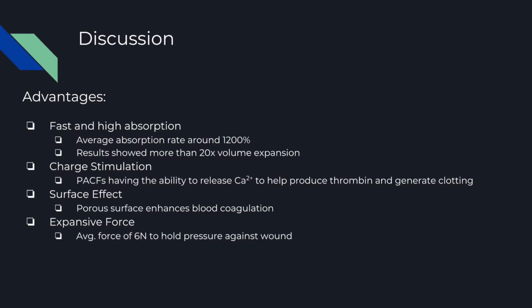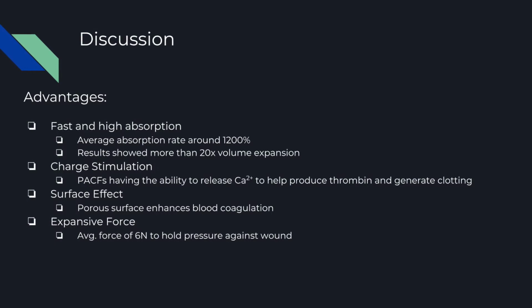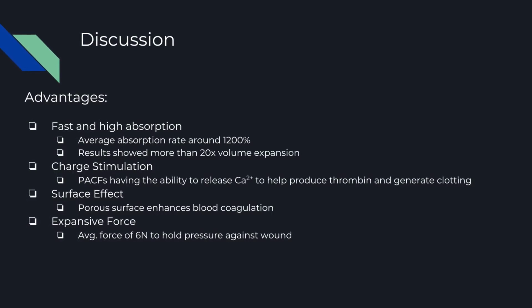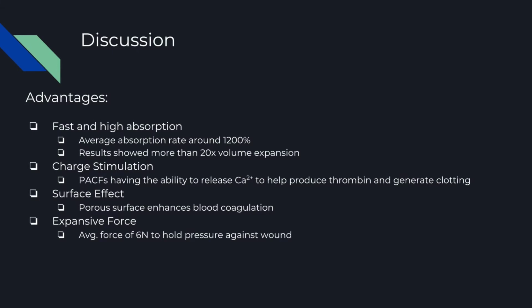The surface effect is a third important advantage of the PACFs. This is attributed to the porous surface of the PACF coupled with the high roughness, which induces the fibrinogen absorption and blood cell adhesion, thereby promoting the formation of the thrombus in seconds. The fourth and last advantage is the expansive force of the PACFs, which averaged a total of 6 newtons of pressure into the large vessels to help stop bleeding.